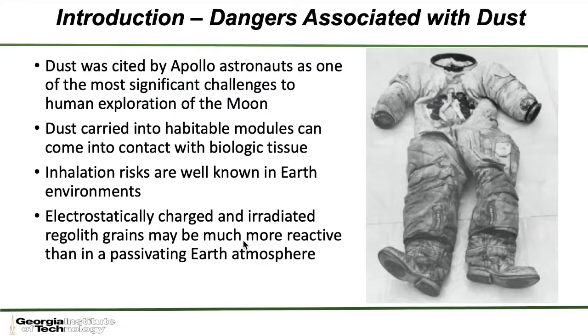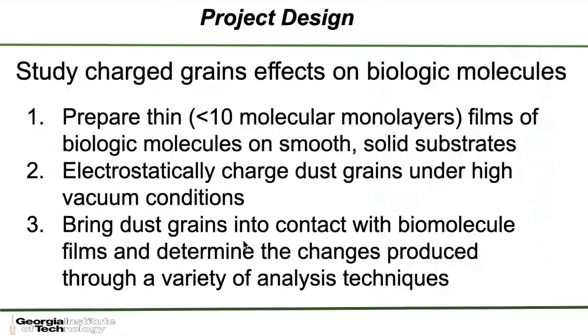So the idea behind the project that I'm going to talk about today is to study the effects of electrostatically charged grains when they come into contact with biologic molecules. The first step is to prepare thin films, and when I say thin, I mean on the order of a few molecular monolayers, thin films of these molecules on some smooth substrates. Step two, independently of step one, is to get these grains electrostatically charged under high vacuum conditions. And then finally, the third step is to bring those two facets together and bring those electrostatically charged dust grains into contact with the biomolecule films and look at what changes are caused in those films as a result of that exposure.